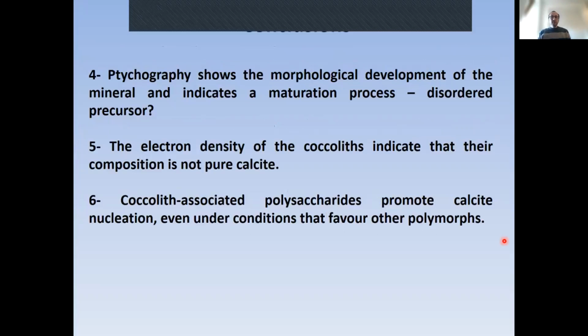With ptychography, we could see the morphological development of the mineral, and that indicates that there is some kind of maturation process going on there, perhaps through a disordered precursor, a highly hydrated precursor. It's also showing that the composition is not purely calcite. We're still trying to understand what is happening there. And the polysaccharides promote calcite nucleation, even under conditions that favor other polymorphs. And that again raises interesting questions about the chemistry in the vesicle and of course the function of these polysaccharides.